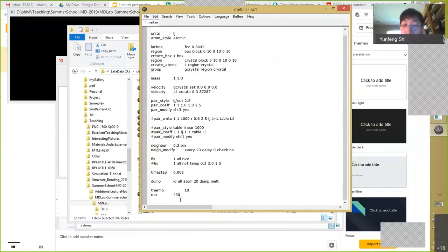Now, I do want to go back to check whether the total energy is conserved, maybe something is wrong with this LAMMPS code. I have to check. This is my habit. Whenever I download a newer version of LAMMPS, or whenever I run a new set of parameters or a new molecular system, I always run NVE first to check the total energy. This is the first thing, a sanity check, okay?